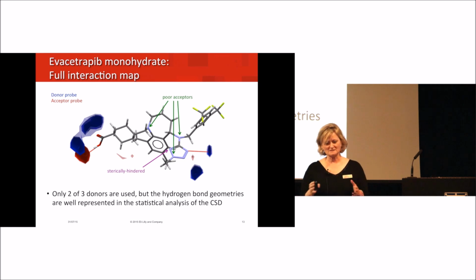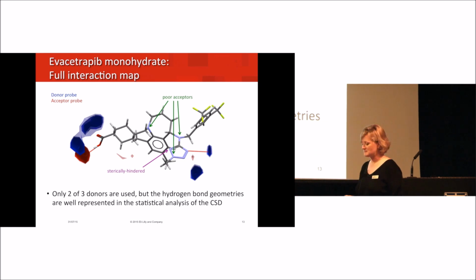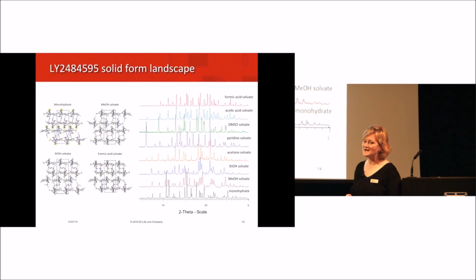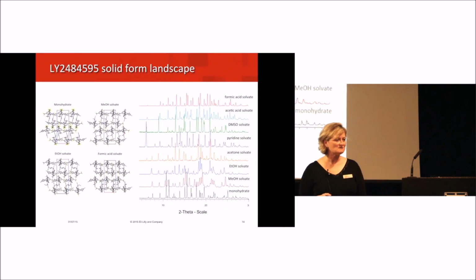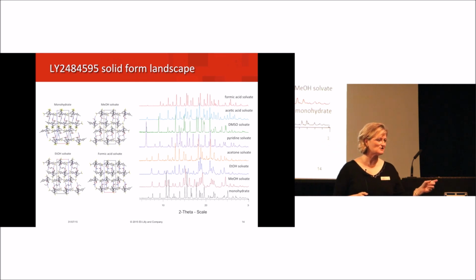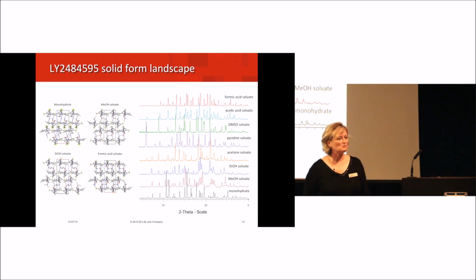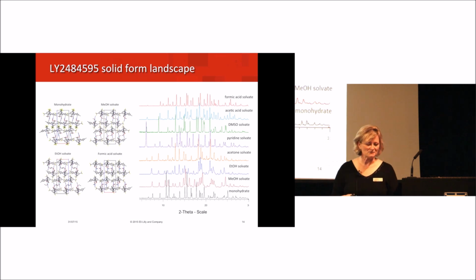So we're looking holistically at these risk assessments. We certainly would have continued our search for solid state forms. And in fact, once this material crystallized, once we had the monohydrate as a starting material, we could crystallize all sorts of forms. In fact, many of them were actually structurally related, as you can see here. And for us, we were lucky because really only one of them stood out as the crystal form that we could develop. So we continued along that pathway and had beautiful crystallization developed from isopropyl alcohol.